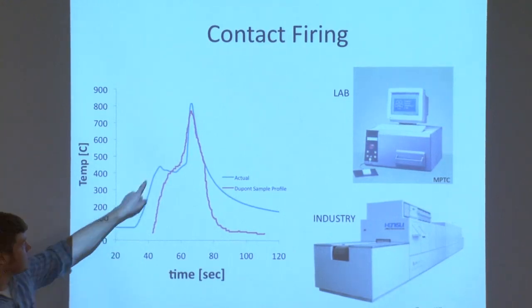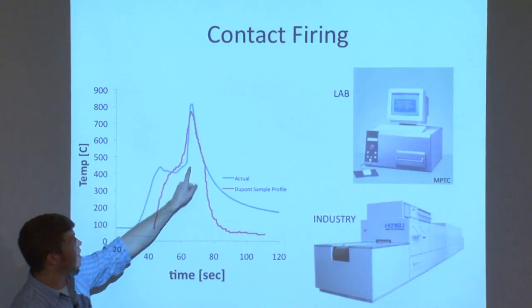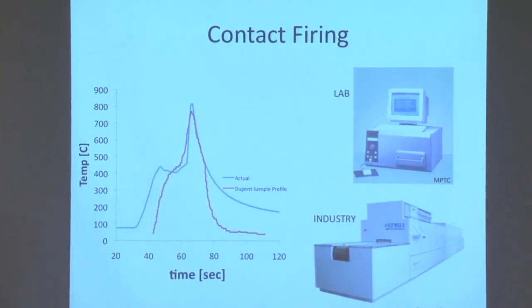So when that happens, this is that burn-off period. When it spikes, the frit will actually burn through your silicon nitride layer. You guys didn't have a silicon nitride layer, but if it was there, it would help eat through it. That way you remove the dielectric so you can actually make metal contact with the silicon surface underneath.